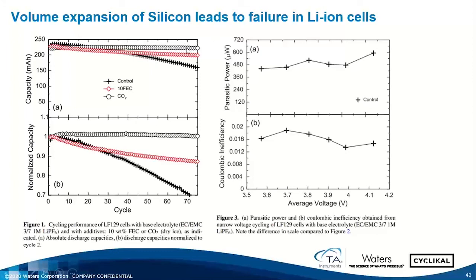So we have three cells. The positive and negative electrodes are all identical. We have the control, which is just ethylene carbonate, ethyl methyl carbonate, and that's the black line here. It might be more useful to look at the normalized capacity. So here's the control. If we take 80% of capacity as the dead point, our cell is dead, and we don't even get 60 cycles out of this electrode. But if we add 10 weight % fluorinated ethylene carbonate, you can see a dramatic increase in the cycle life. And if we add a source of carbon dioxide, you can see what happens to the cell cycle life. It's dramatically different. So let's turn to the parasitic power signal and the Coulombic inefficiency.